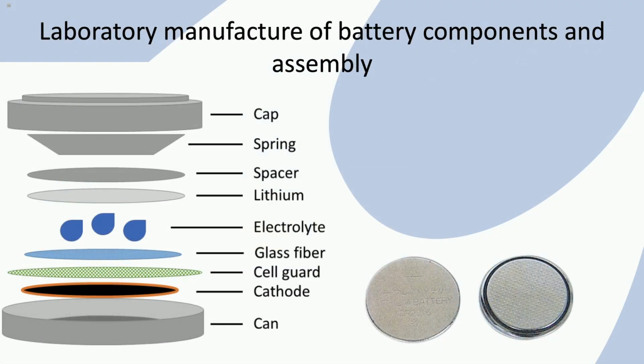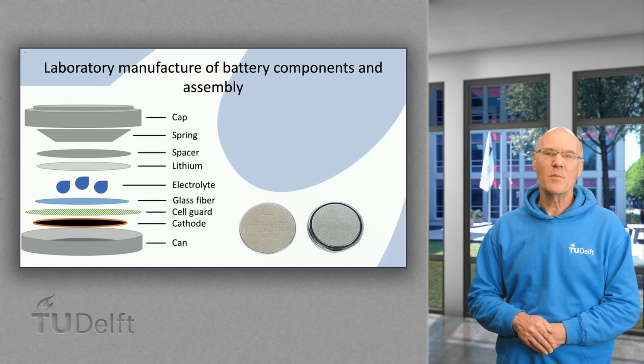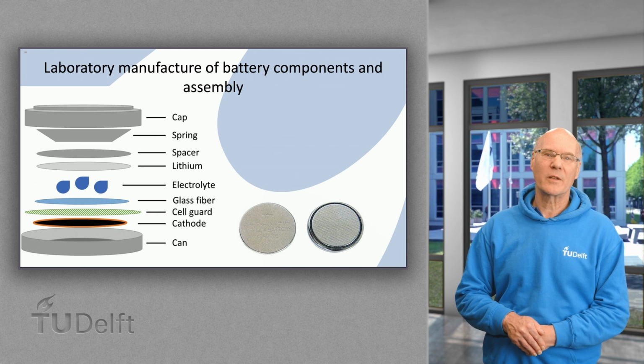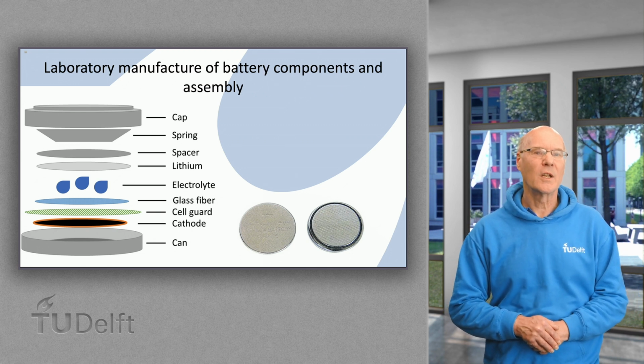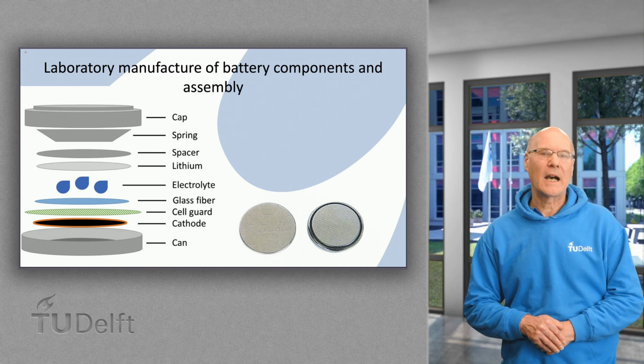In a commercial industrial process, similar steps are being carried out, but using a glove box is not practical, and therefore that part of the processing is being done in a very low moisture content environment. This is often called a dry room with a dew point of say -20 to -40, which means that the water vapor pressure agrees with an atmospheric temperature of -20 or -40 degrees C. So let's see how that then goes.